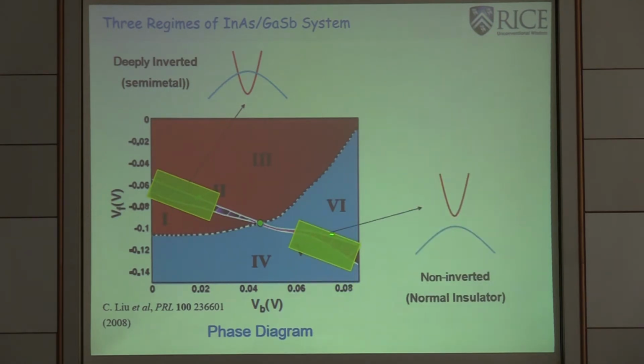Now, if you go to the opposite, the other side of the phase diagram shown here, basically you have a normal insulator or semiconductor, the usual semiconductor. What is interesting is the regime between this semi-metal and the semiconductor. You have some region where the density is low enough. How low is low? In this case, 1 × 10^11. That's the typical number we have.